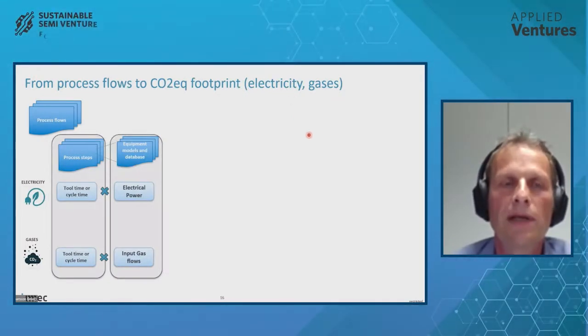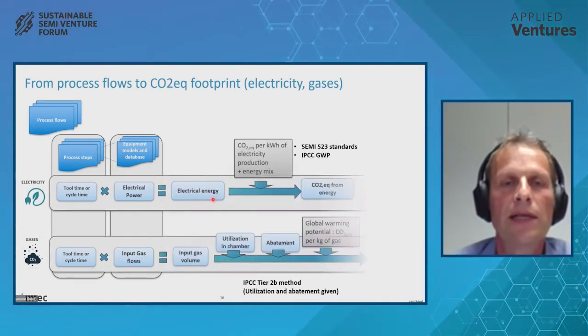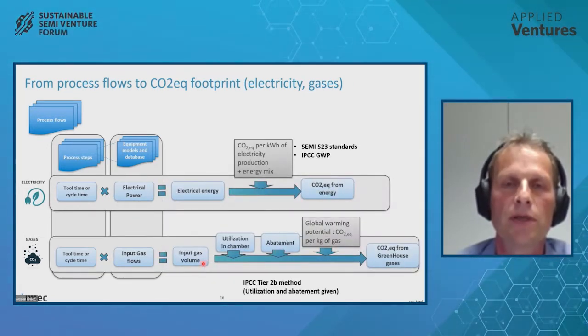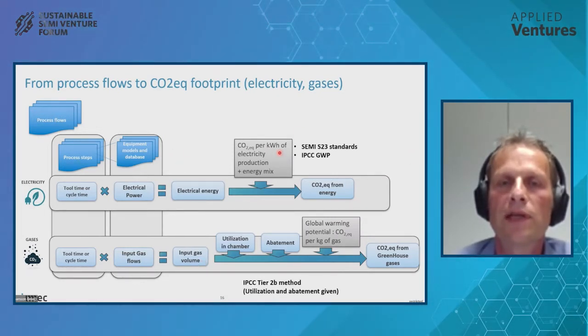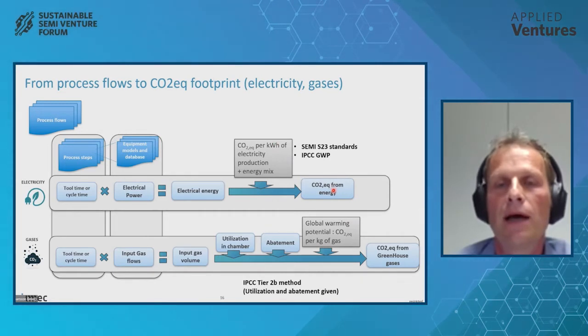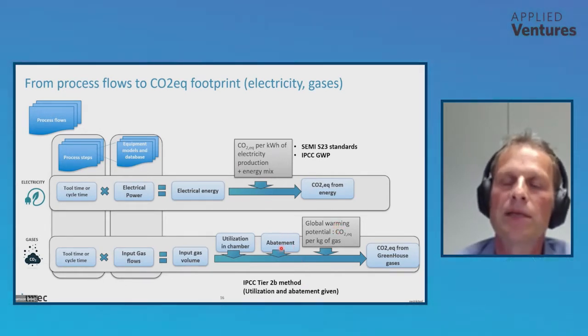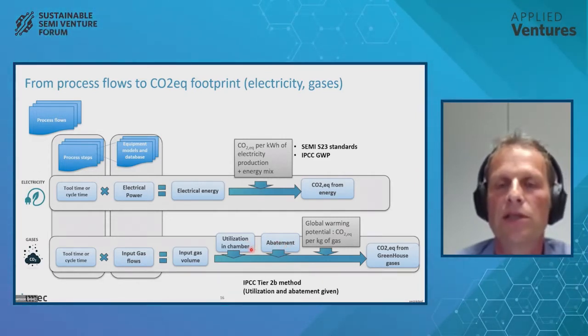To do that, we use a lifecycle analysis, and we base that on our process flows that we have, which have a lot of process steps that are coupled to different tools and recipes. And by doing that, we can then estimate what the electrical energy used is and how much of the gases we are using. Then we use standards to actually convert the electrical energy into the CO2 equivalent based on an assumed energy mix. And in the gas case, in the direct emissions, we use the global warming potential for the different gases and make assumptions on abatement and utilization in the chambers. And then finally, we can add these two up to have most of the emissions from the process.